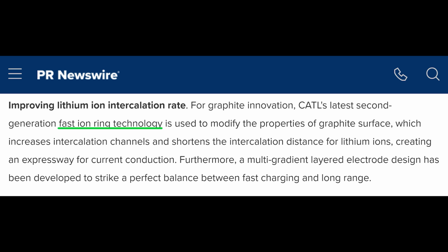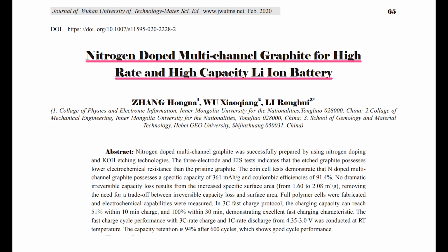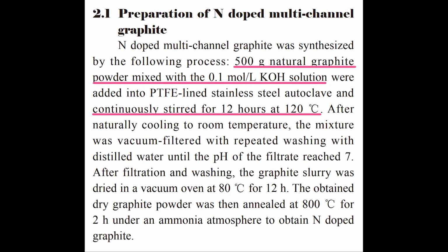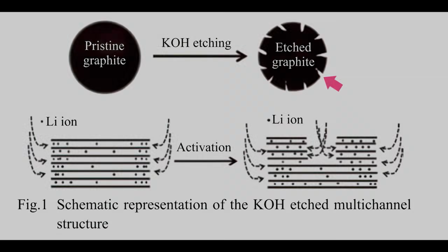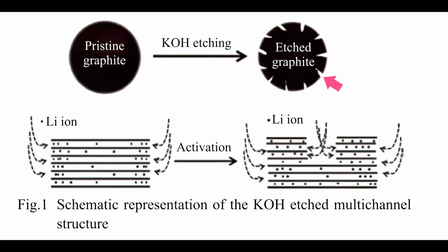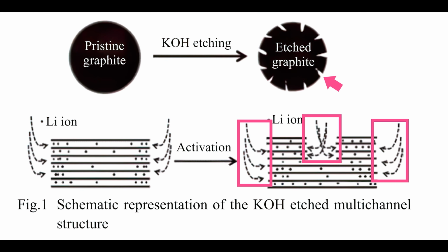However, when CATL said fast ion ring, it made me think of this paper from 2019 by Zhang et al., titled Nitrogen-Doped Multi-Channel Graphite for High Rate and High Capacity Lithium-Ion Battery. That paper caught my attention a few years ago because it seemed like a simple and low-cost way to increase charge rate. It involved just 2 production steps. First, the graphite was stirred in an alkaline potassium hydroxide solution at low heat, then dried. That etched the graphite, or created grooves in it, which created greater surface area for lithium ions to enter and exit the graphite more quickly.